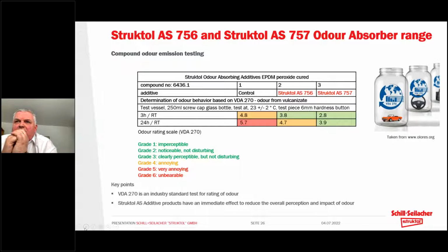In carrying out this test, and we carried it out a number of times and even sent it to an external accredited laboratory and arrived at the same numbers within the same rankings, we can see the 3 compounds behave quite differently. Compound number 1, the control compound, goes from a concern level to a red level between 3 hours to 24 hours after placing in the sample bottle. So we have a concern to an unacceptable rating. Whereas with the 2 different additives, the pastille additive as part odor absorber, part lubricant, we go from acceptable to concern. And with the dual acting product, we remain within the acceptable low odor range over all of the test times that we measured. Next, please.